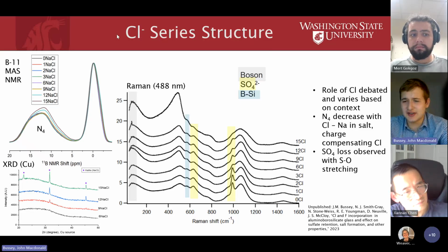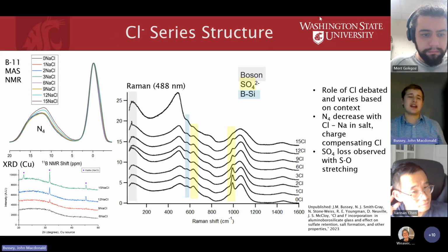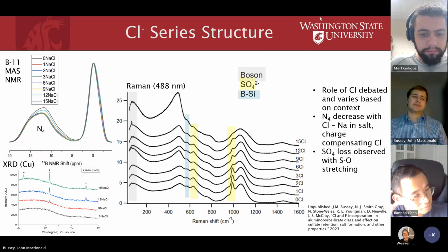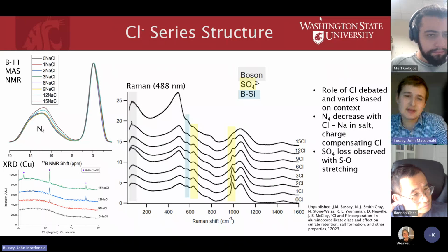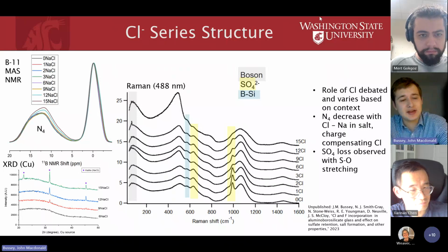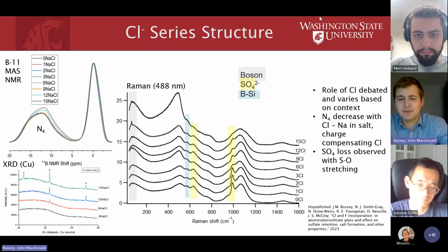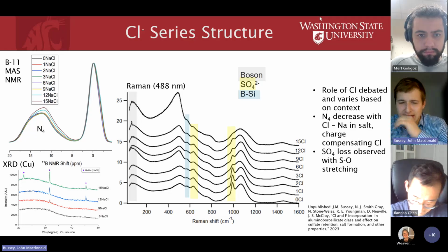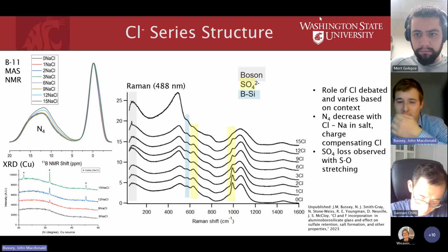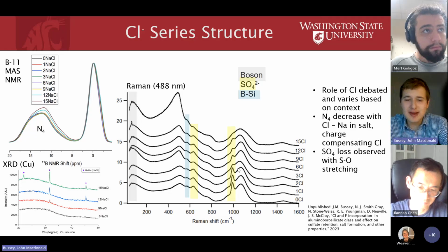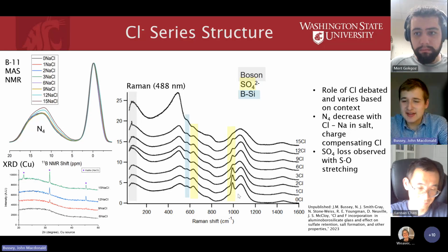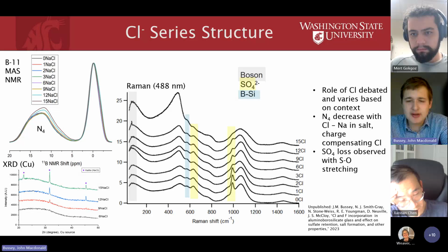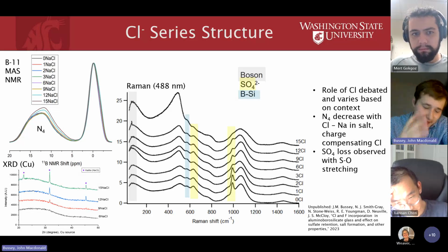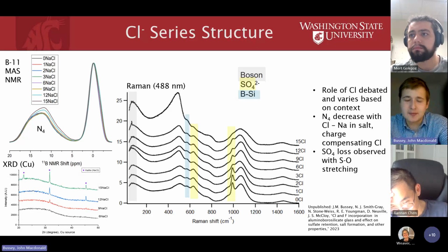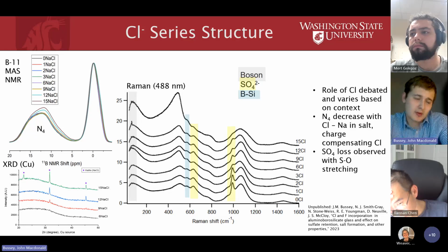To understand the structure, we looked at NMR, nuclear magnetic resonance, Raman spectroscopy, X-ray diffraction, and a variety of other methods to try to understand what's going on. In the Raman, the main thing we observe is that at higher chlorine loadings, all the sulfur goes away, right? That corresponds with what we saw from the elemental measurements.